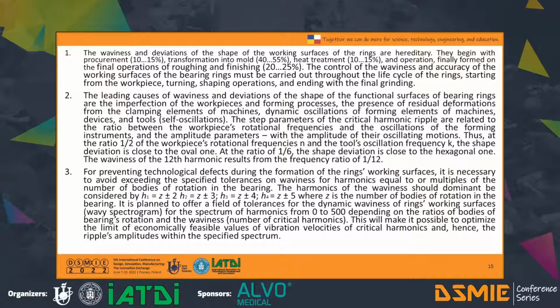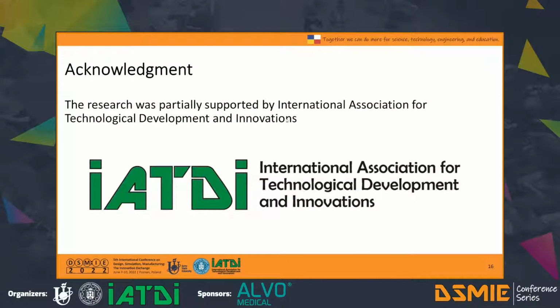It is planned to set a field tolerance of the dynamic waviness of the ring working surface for the spectrum of harmonics from 0 to 500, depending on the ratios of bodies of rotation and waviness. This will make it possible to optimize the limit of economically feasible values of vibration velocities of critical harmonics, and hence of the vibration amplitude, which specifies the spectrums. And acknowledgement. The research was partially supported by the International Association for Technological Development and Innovation.